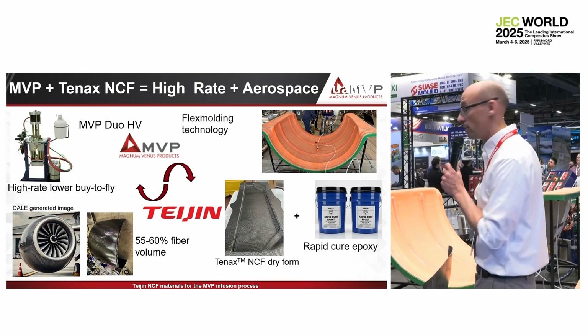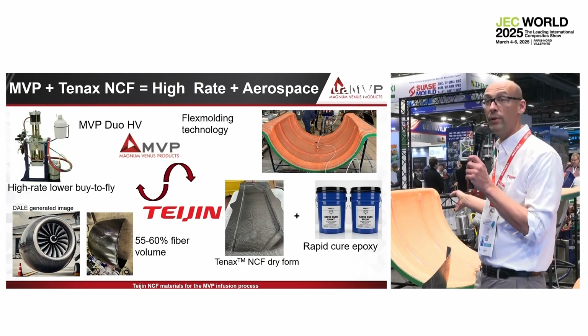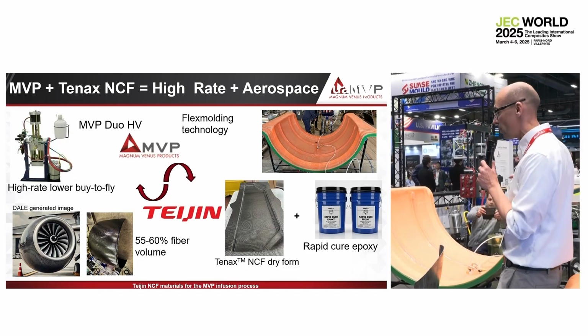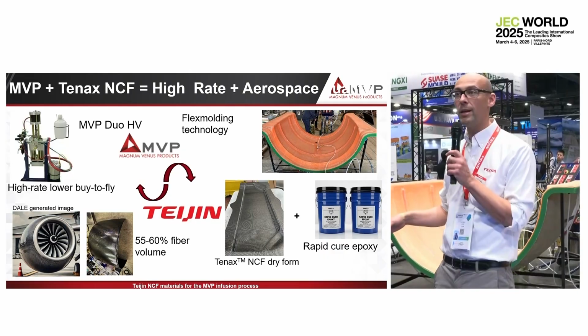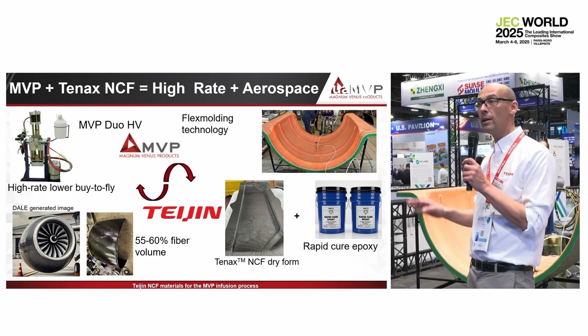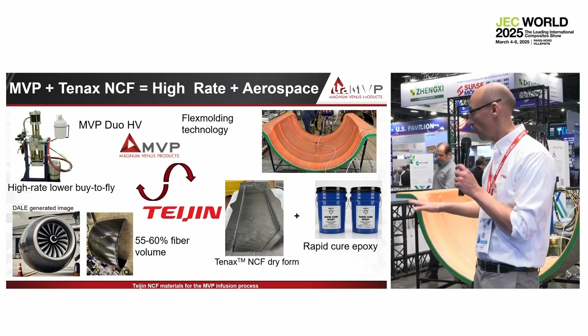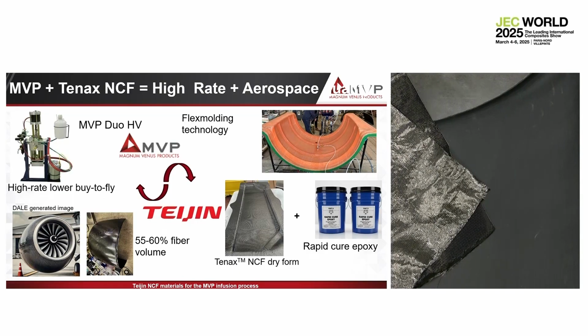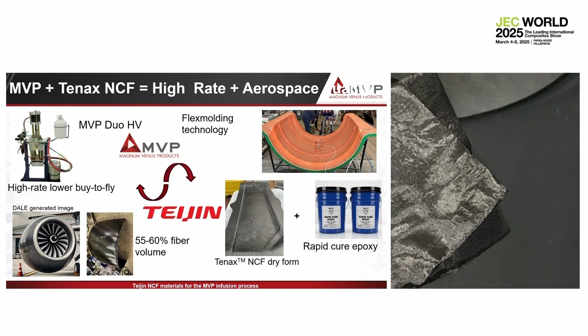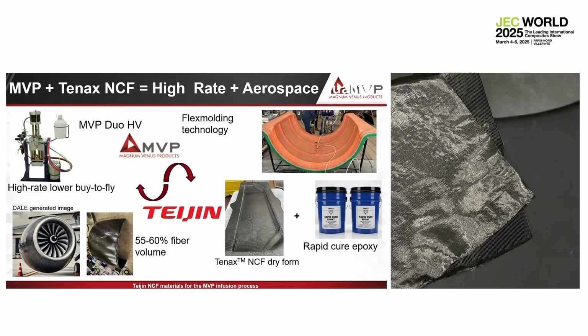And we made it with this mold right here in under about a 15-minute infusion, which Charles is going to show you. The first layer is a high drapeability, intermediate modulus fiber for stiffness. It's low area weight, and it's going to conform well. We don't have this part up here, but there's no wrinkles.